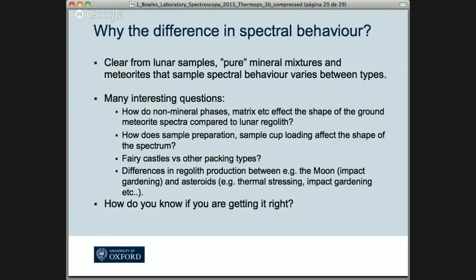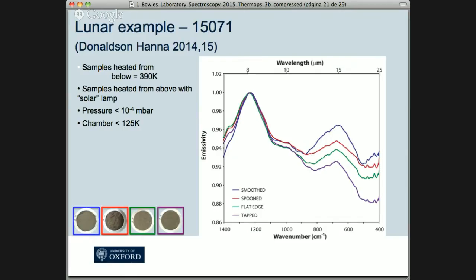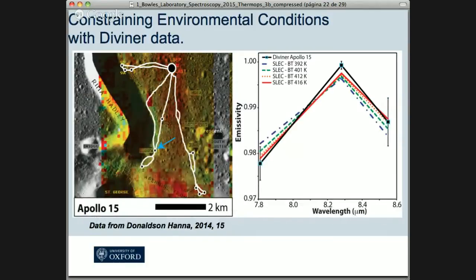More importantly, how do you know if you're getting it right? So one of the things that, again, Kerry had been working on was loading our sample cups in different ways and looking at how the spectrum moves around. This was for direct comparison to Diviner data. And you can see that we get some differences in spectral contrast between the CF and the Reststrahlen bands, depending on how we load the cup. But importantly, the CF position doesn't move, which for Diviner is the key thing. And we can then go back and compare that to Diviner data from, say, looking at the exact site. This is one of the advantages of the Moon. It's one of the great fun things we're going to have with something like OSIRIS-REx, is because we will know where we've gone.